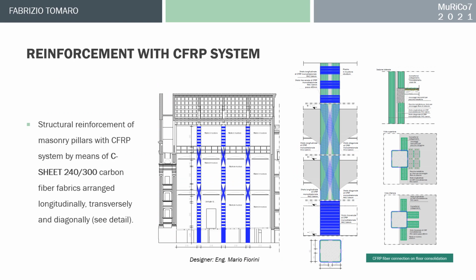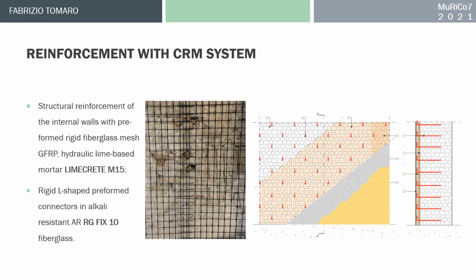The consolidation intervention concerned first of all the masonry pillars, on which a structural reinforcement was planned through carbon fiber fabrics of 300 grams per square meter applied according to the provisions shown in the figure. Drawings were provided by the engineer Mario Fiorini. For the structural reinforcement system of the internal walls with the CRM reinforced plaster, it was decided to apply a preformed rigid fiberglass GFRP mesh with M15 hydraulic lime-based mortar and alkali resistant glass fiber L-shaped rigid preformed anchor connectors.